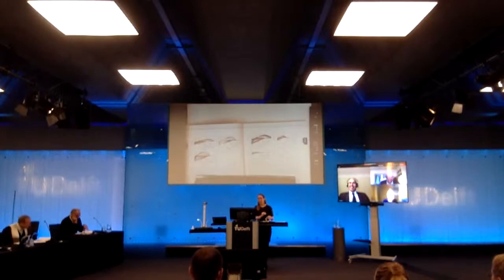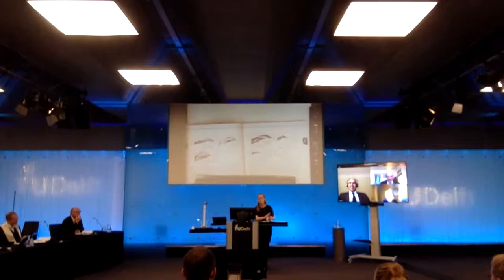Oh, that's actually true, and I have performed those measurements. I just didn't think about it, but I only did them once to show the proof of concept that we see intraband transitions in zinc oxide. But I only did it with lithium. I have it in one of the appendixes if you are interested.